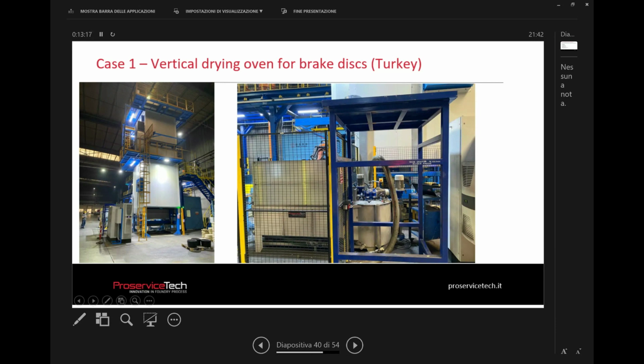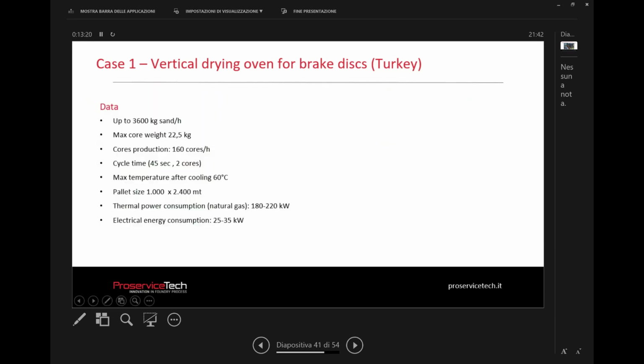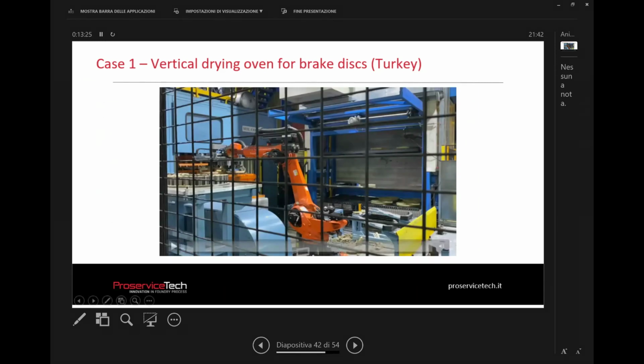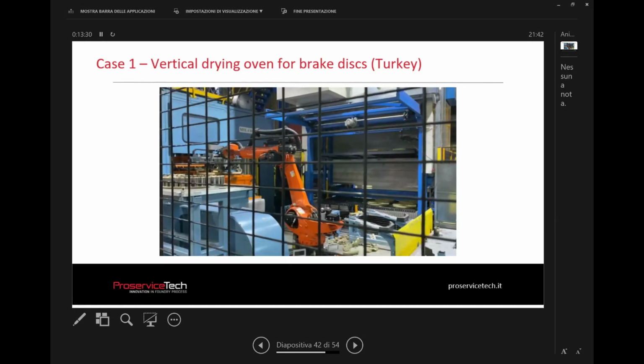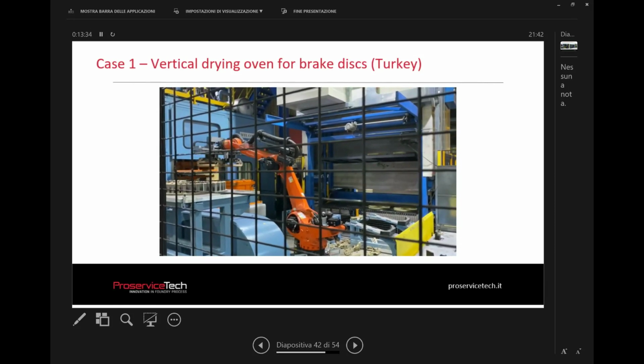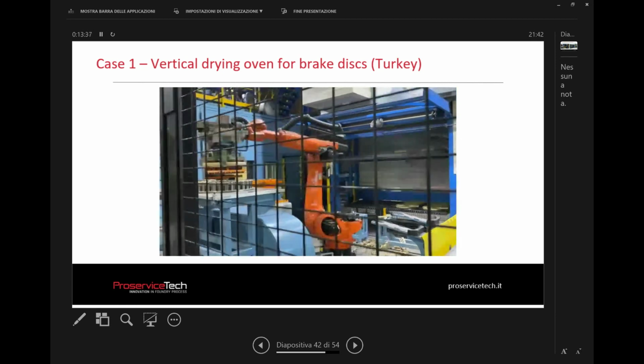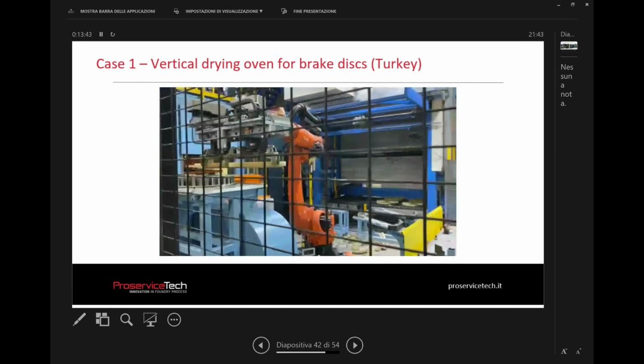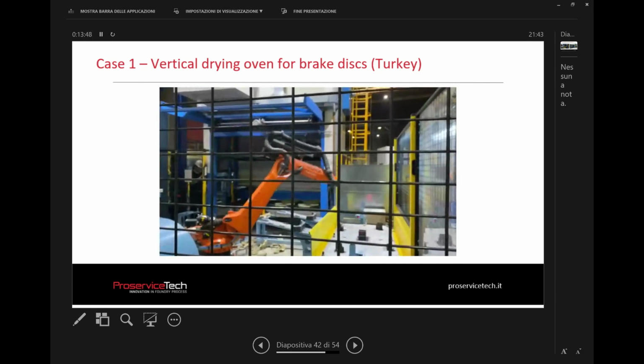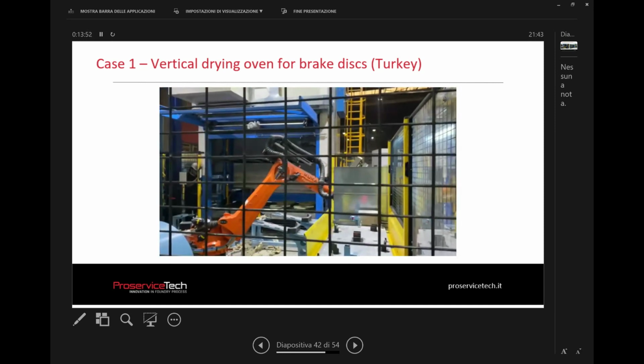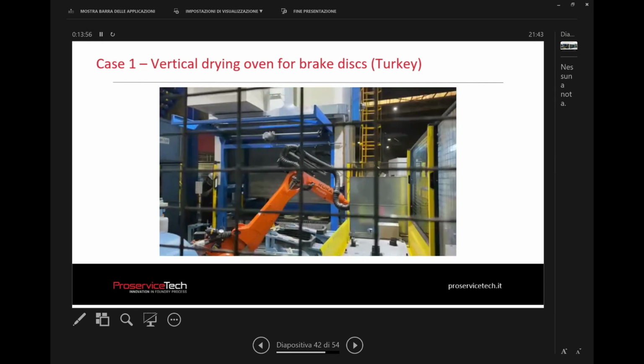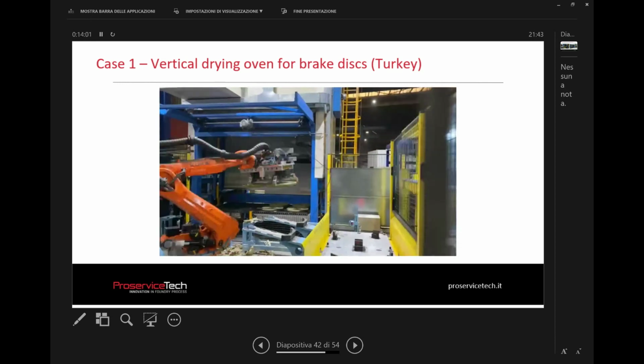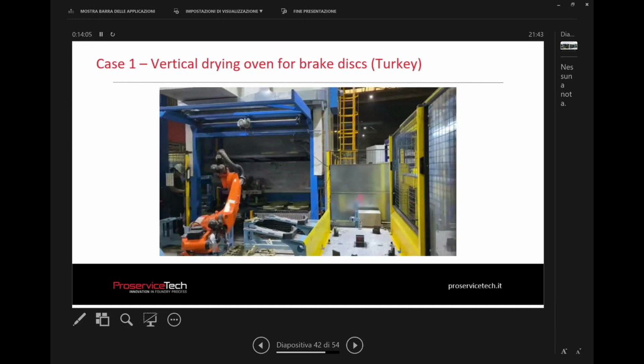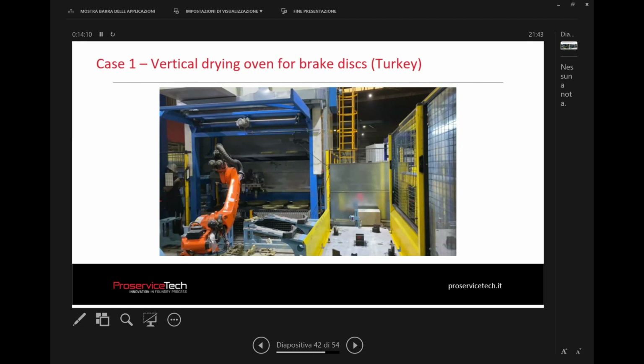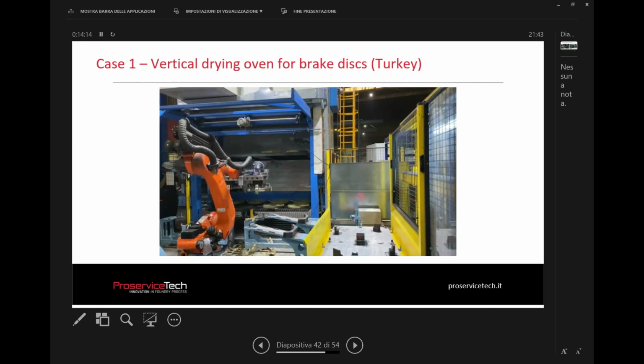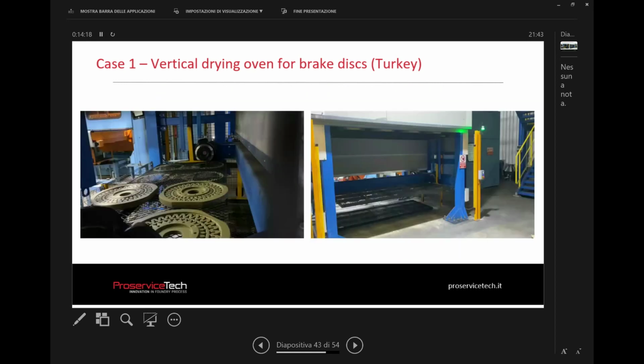For example, this is Ecufren. We have delivered 2 of these vertical ovens for brake discs, with robots, so directly from the core shooter to the drying oven, with our dip tanks also. The dip tanks are not easy to see, but they are there. In this foundry they did not have enough space for placing a long drying oven, so we went up to 11 meters.